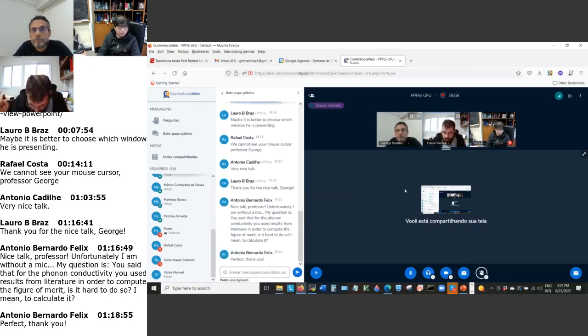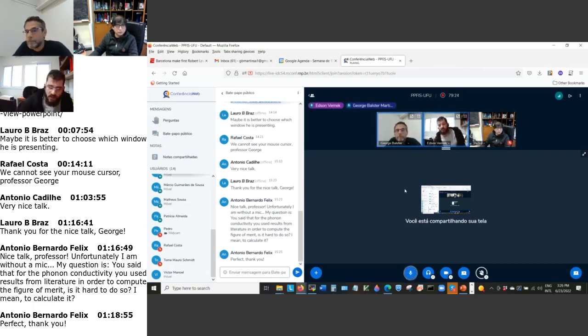So in connection with the phonon scattering, let me start a little bit before. In your case, the clean, pristine graphene nanoribbon, it's metallic, right? Depends on M, right? Yeah. So if it's metallic, it's not good. It does not show a good thermoelectric effect. Yeah, ZT is very low.